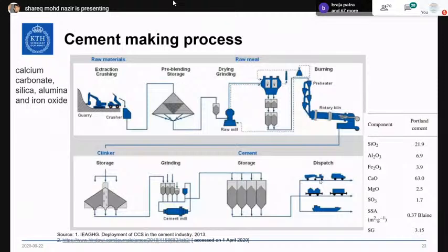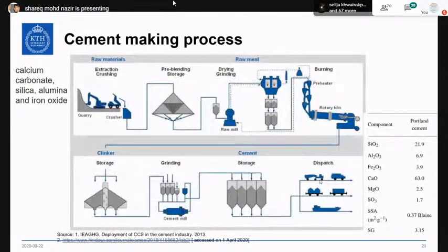So after that, this forms clinker. This clinker is stored, it is ground, and then cement is basically prepared after grinding the clinker. So when you speak about cement, the composition of cement is on the right side, which has 63% calcium oxide. So the major step here is the calcination step, which happens in the kiln.